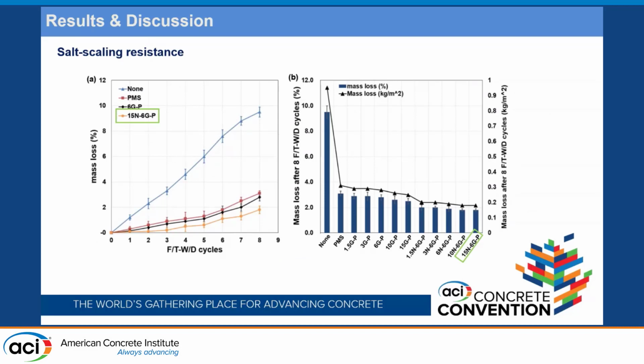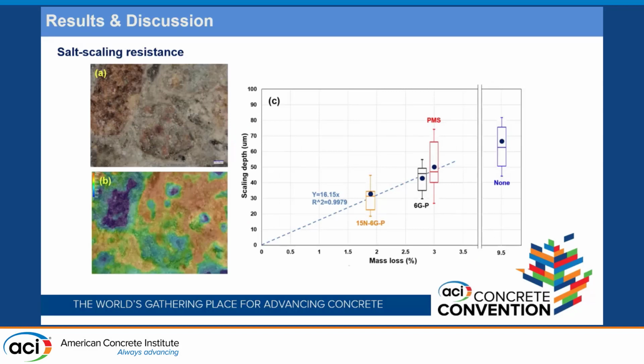Here is the salt scaling resistance. As we can learn from these two figures, after adding these two nanomaterials, the mass loss during the freeze thaw process is decreased greatly. Here we test the surface roughness of the selected samples, and we find the introduced nanoclay also helps to mitigate the surface scaling. As I mentioned earlier, surface scaling distress happens when water comes into the concrete with the salt. So the reduced water absorption and reduced gas permeability will help to enhance the salt scaling resistance.